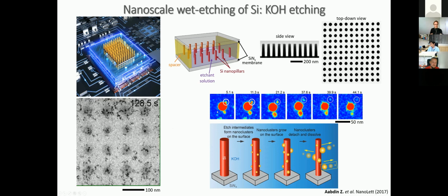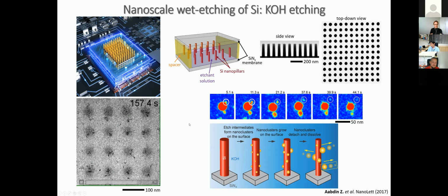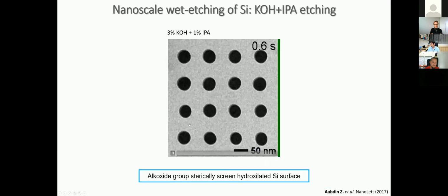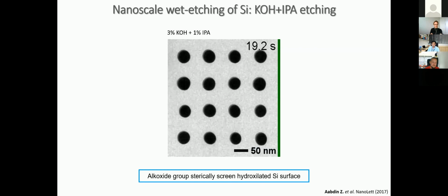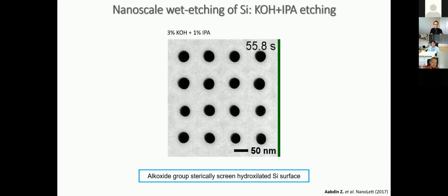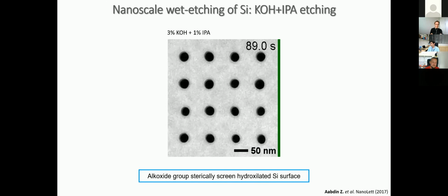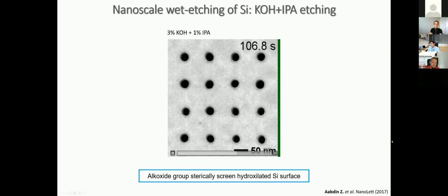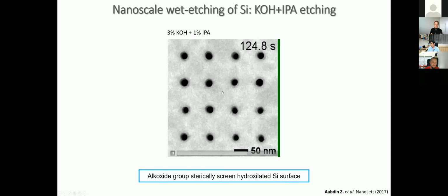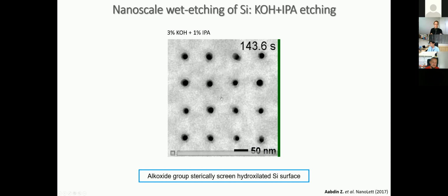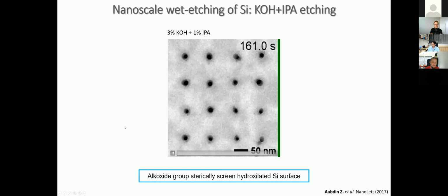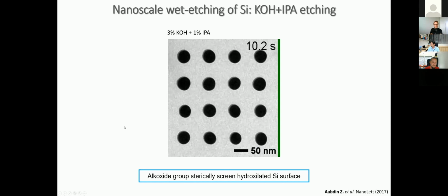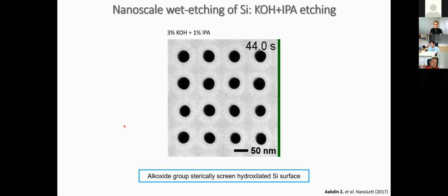So then, because we understand now what's happening, can we prevent the nucleation of these byproducts on the surface? And it turns out yes, because we understand the surface chemistry and what modification to surface chemistry happens during the etching. And it turns out adding a trace amount of alcohol, or pretty much any organic that can passivate the surface, actually prevents the nucleation of the byproducts. And what you see here is essentially smooth etching with very little or almost no byproducts forming on the surface. Again, I'm not going to go into details, but this is just because we can watch, understand what's going on, and then we can actually improve the process.